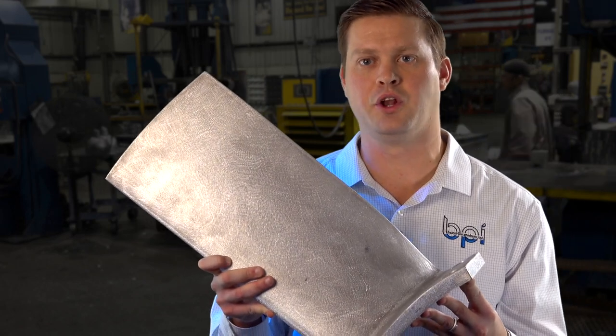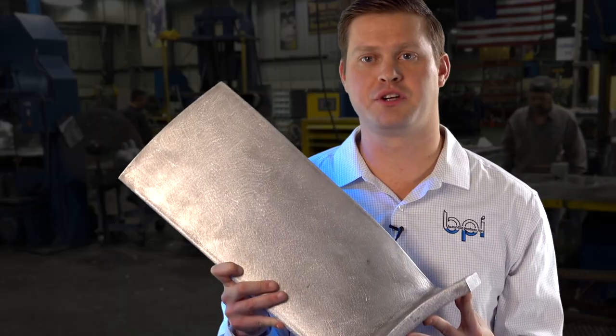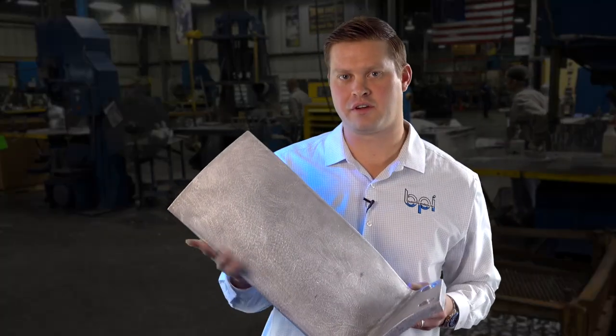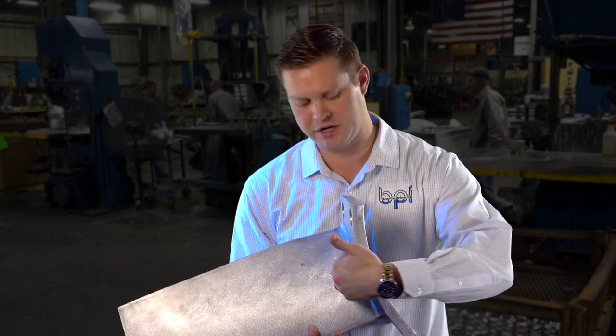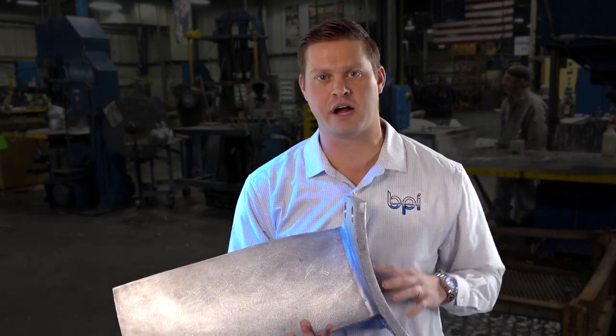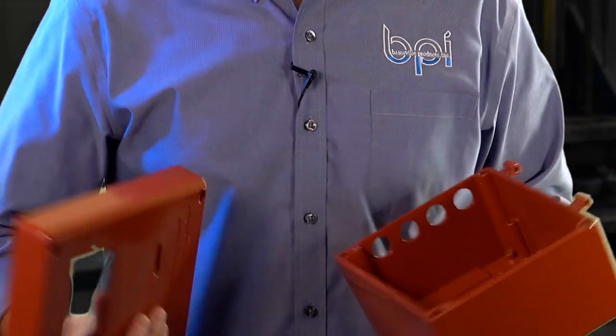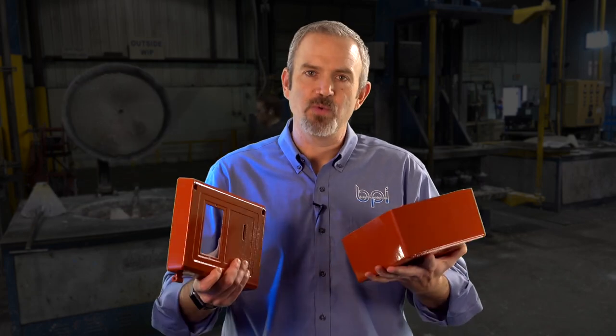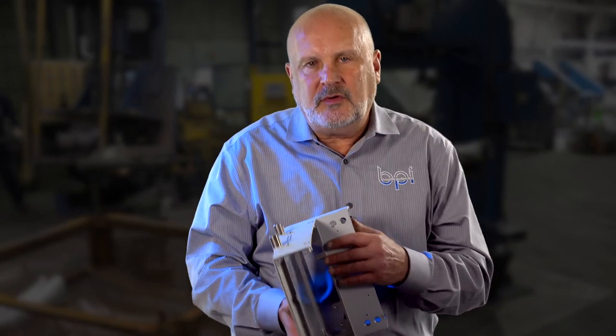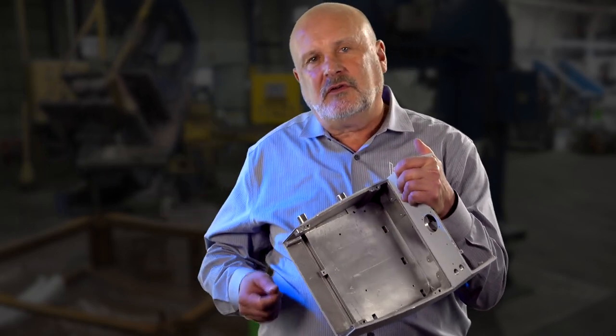Picture this piece on a 72-inch fan on a locomotive. The customer came to us with issues — they were having hairline cracks down at the base. This was originally cast using a sand casting process, and the customer was casting it from the tip. What Batesville Products did was flip it upside down, have the metal feed through the thick section, really eliminating the turbulence that was creating the hairline cracks. We also have a utility box — we redesigned it, tooled, molded, and cast it in our facility, then sent it off to Craddock Finishing to be coated. This was an off-the-shelf box that we designed and made their own — they branded it and now it's theirs. We also do this for lighting applications, where we cast a tube into the casting like a conduit so wires can pass through.